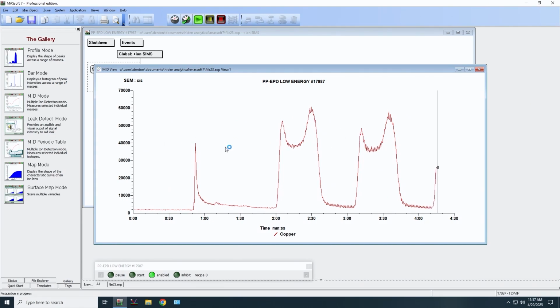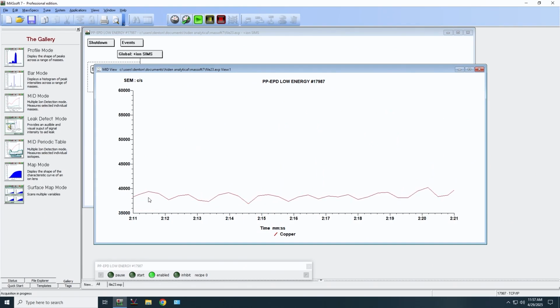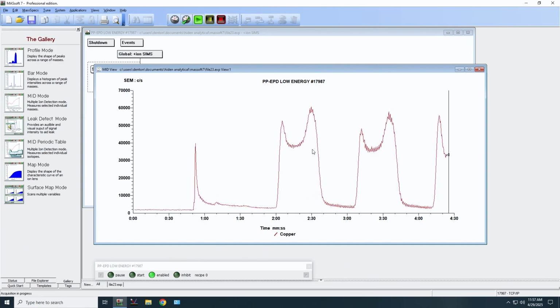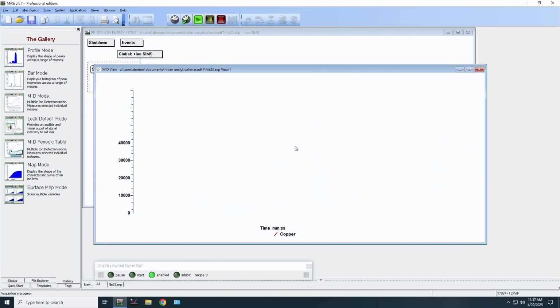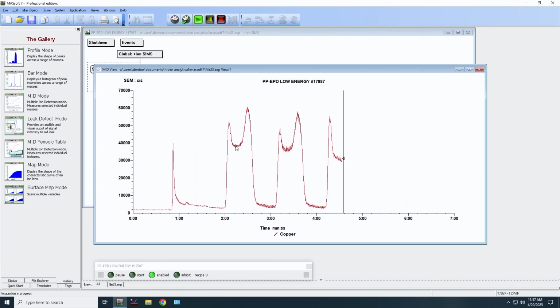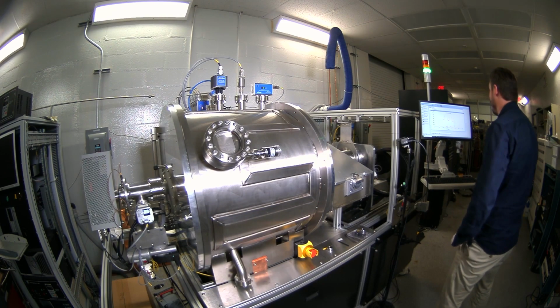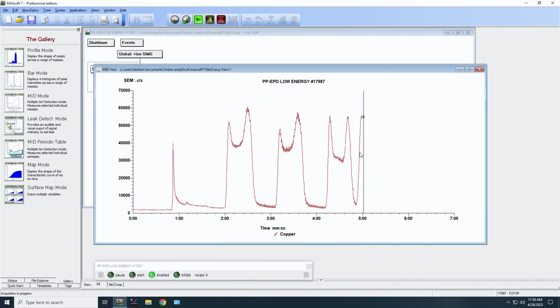Right now the signal at the copper layer is about 38,000 counts per second, which is a pretty good level. That's well above the background of 1 or 2,000. And that is from a chip which is approximately 1 centimeter by 1 centimeter in size. So you can scale that down. With a chip that's 2 by 5 millimeters, you can still observe the copper signal.